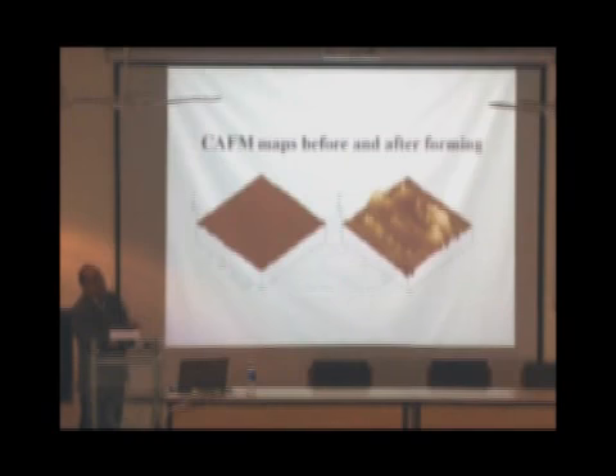And this is a conducting atomic force microscopy picture of this nanorod sample. This is before electroforming, you don't see any variation in the current. This is after electroforming. You can see that individual nanorods, some of them, now show low resistance state, and you observe high current in the conducting atomic force microscope. Again, this indicates that the effect is coming due to the formation of filaments in individual nanorods. So an individual nanorod is acting like one particular resistive memory device.